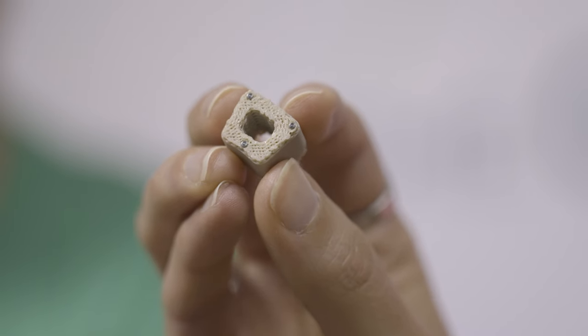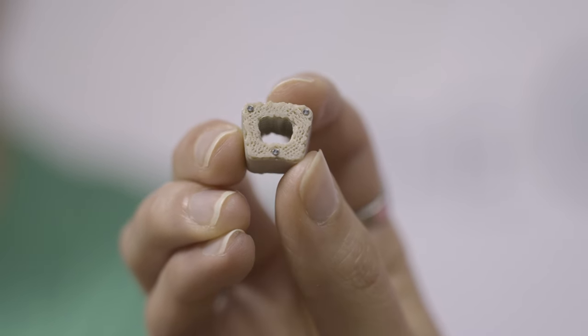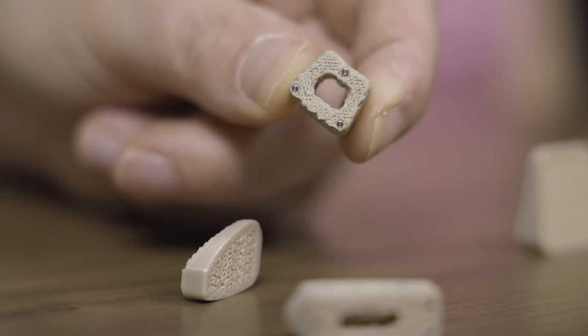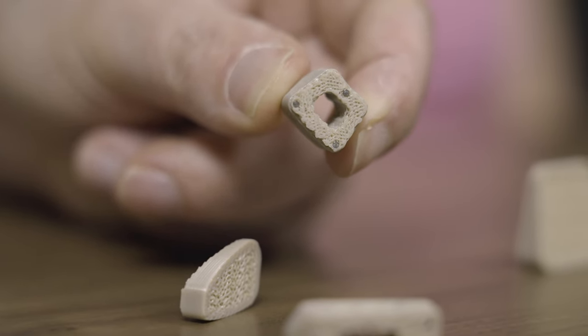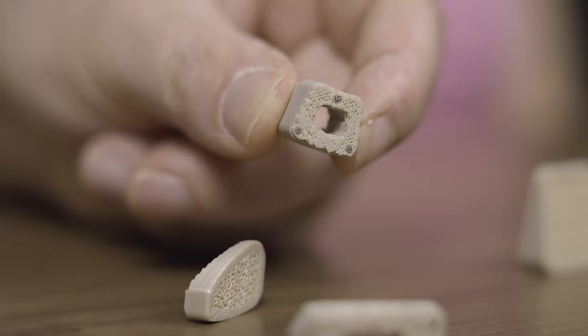Without controlling some of the thermal history when printing PEEK, the PEEK can be locked in this amorphous state, and that'll create this amber to translucent brown streaking within the layers, and also minimizes the mechanical strength on your Z layer bond. And so a semi-crystalline state will be the natural opaque off-white color, which you'll see consistently through the construct in a finished printed device. So the specific 3D printing method that they're using is called fused filament fabrication.